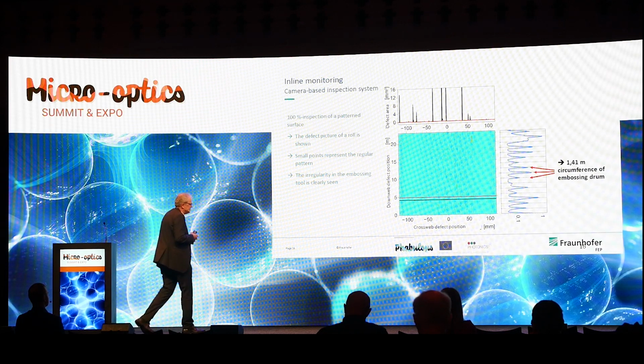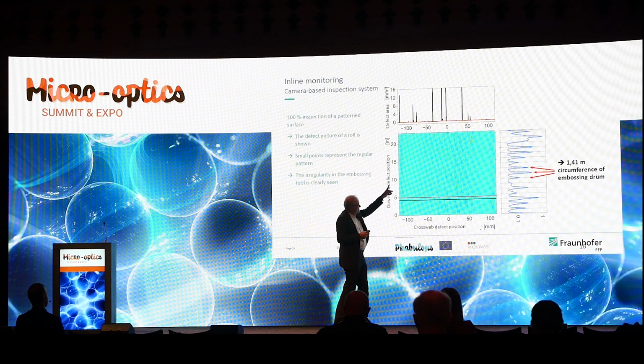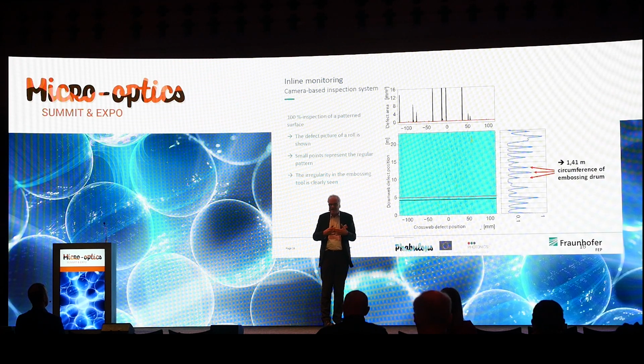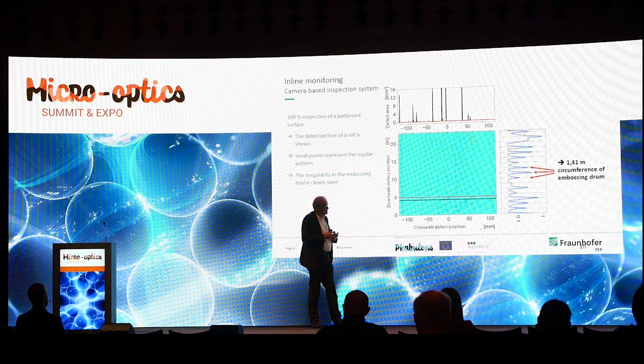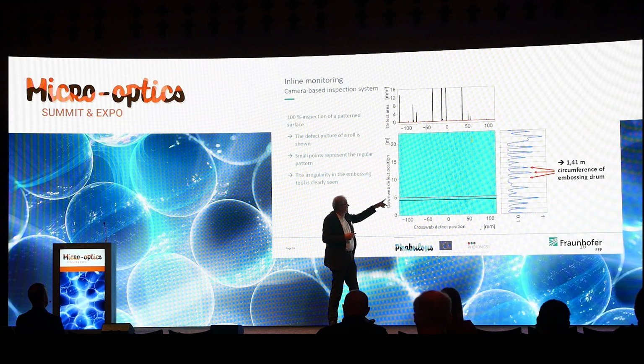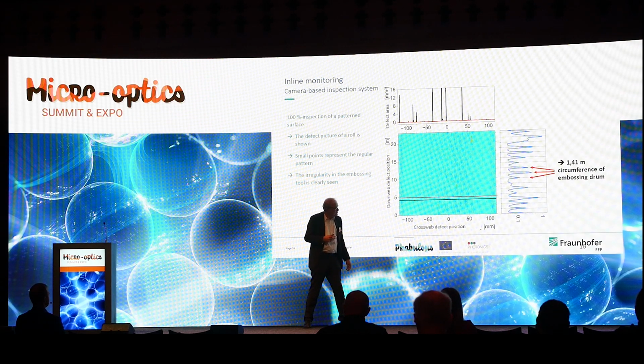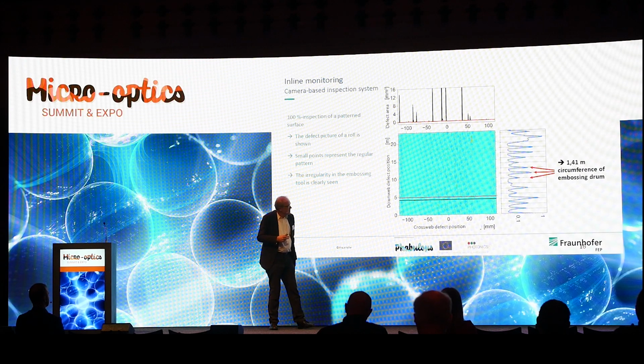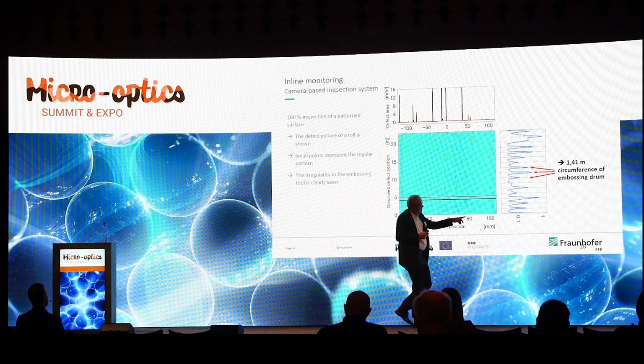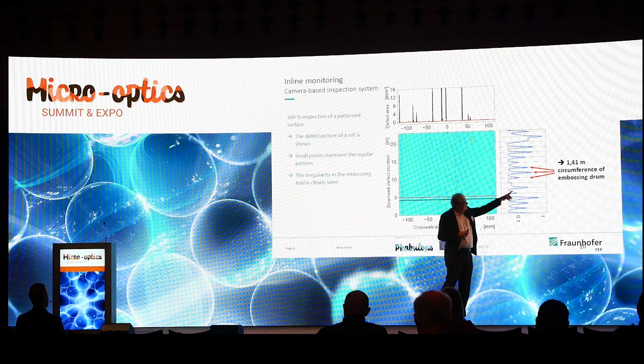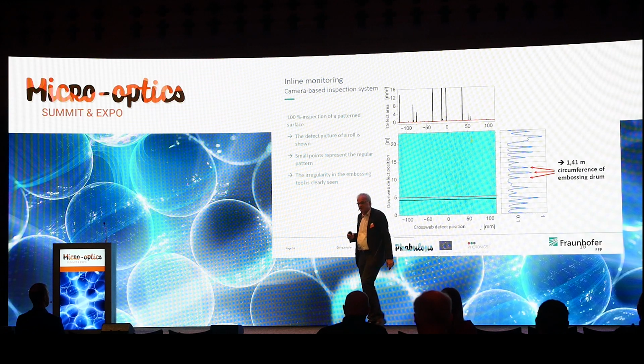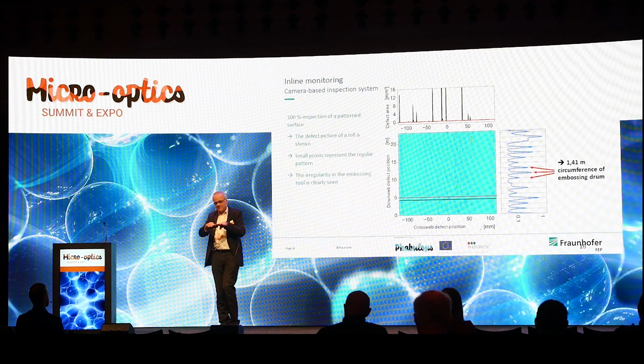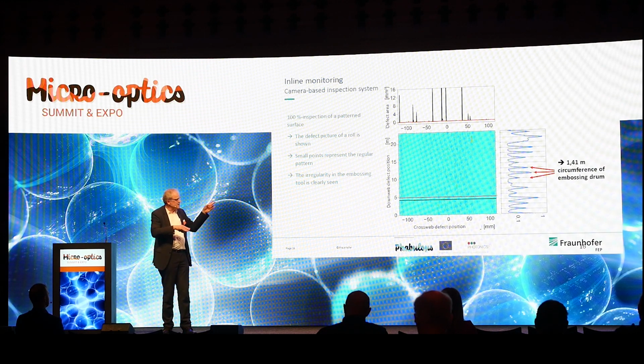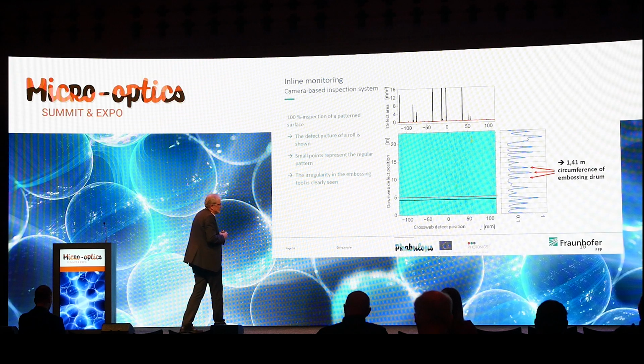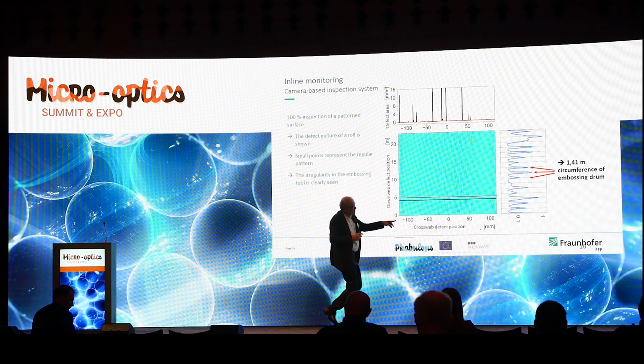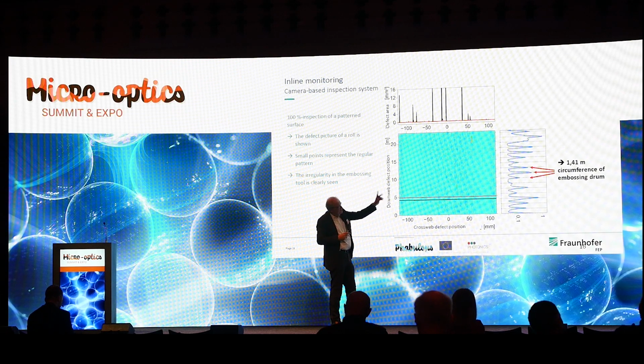So what you see here in the middle of this field are optical signals on the entire film, really the entire area which was coated, or which was embossed also in this case. You have a crossweb position and a downweb position, so different units, as you see. One is millimeter, the other one is meter. And what you can see here is that you have an increase of detected defects in a very regular shape in the downward direction, and that's exactly where you have the touching point of the shim, which was embossing the structure into the film. So you see a very regular distance. The height of the defect is not always the same, but the pattern is very clear. So that's something which is simply due to the shim.